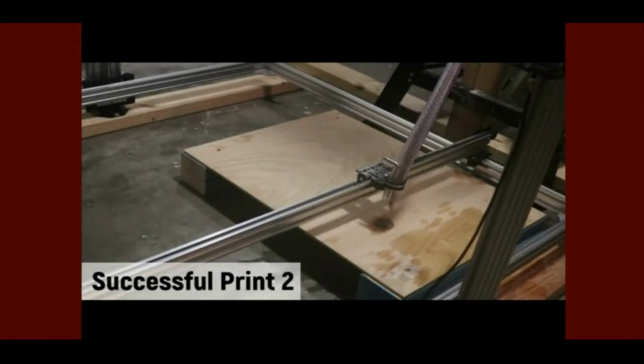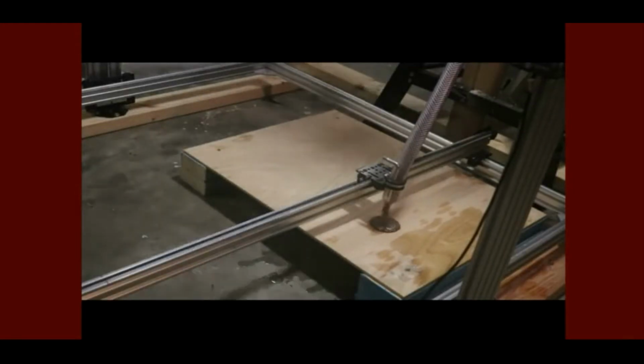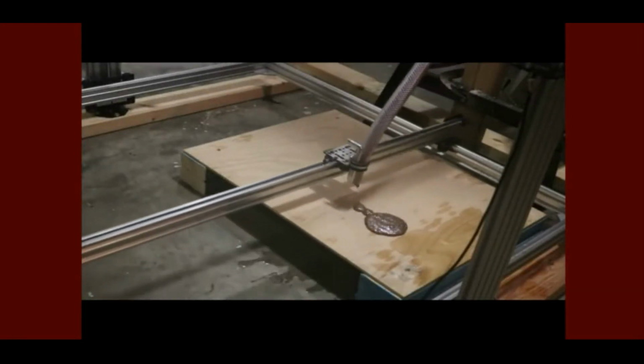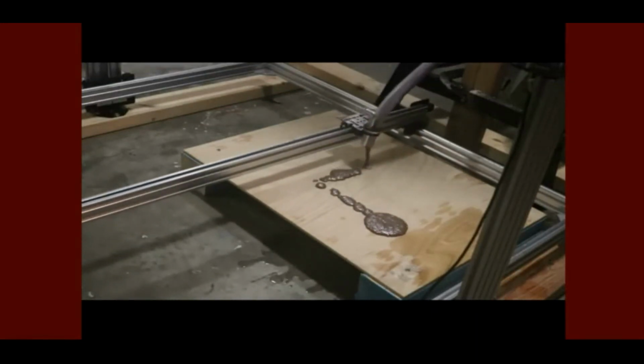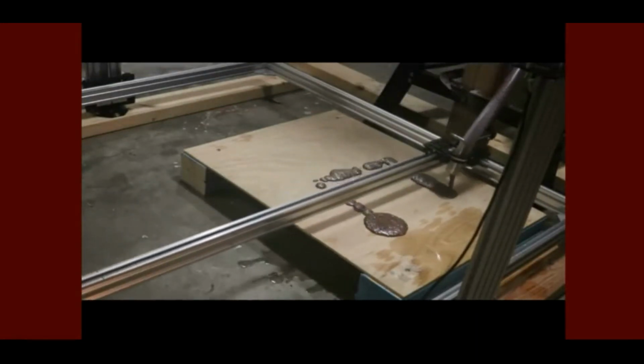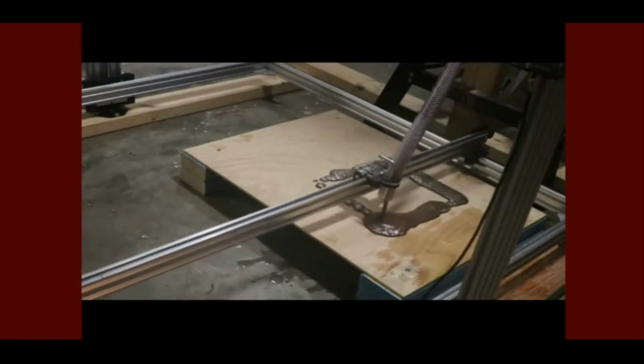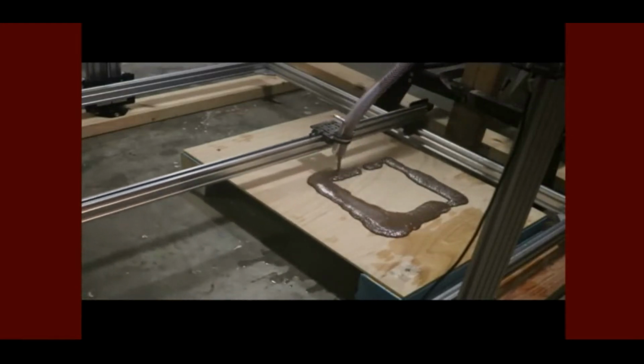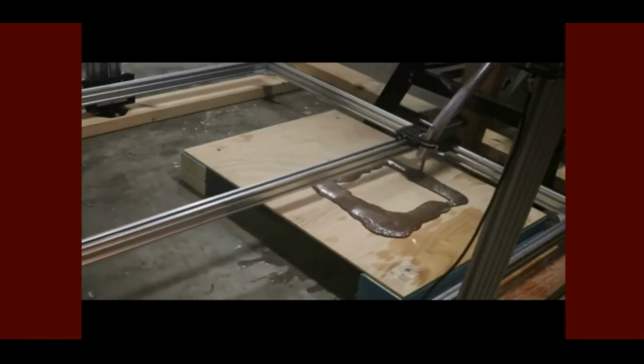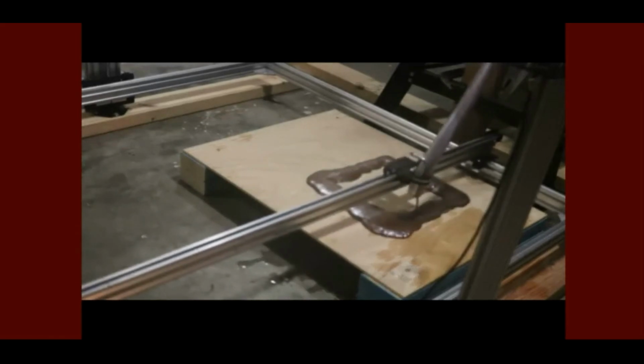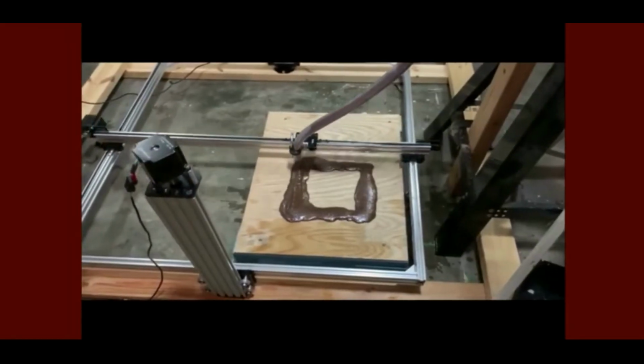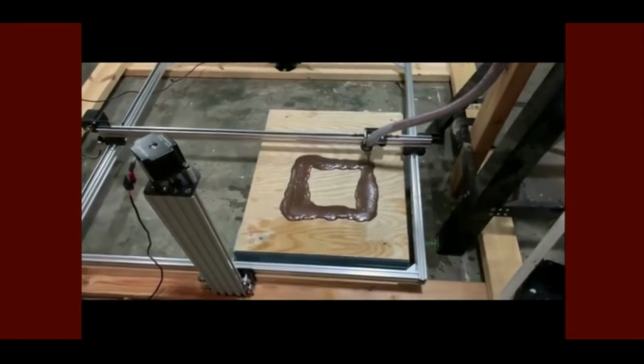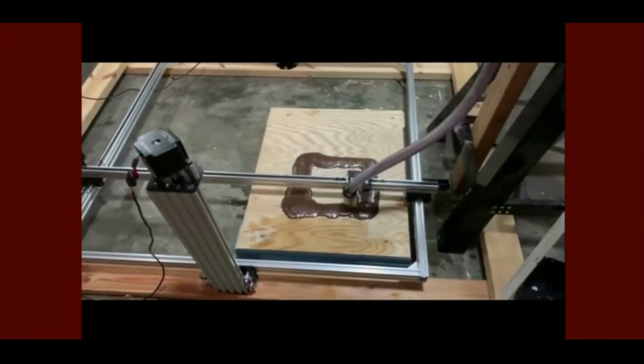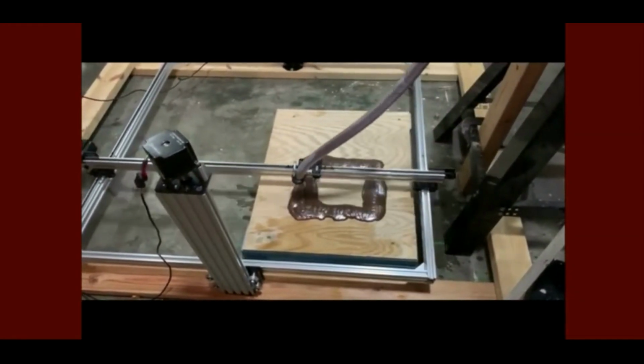And this is another print that I did. And this one, I started the programming more on time, so you'll see it does get to do a few different tracings and start to actually layer up. And you can see it is kind of liquidy, and that comes from having to switch to that less optimal ratio. But because I did determine that more optimal ratio, if I had heated tubing, I would be able to use that ratio, and it would be a lot more precise and actually be better for building up actual structures.